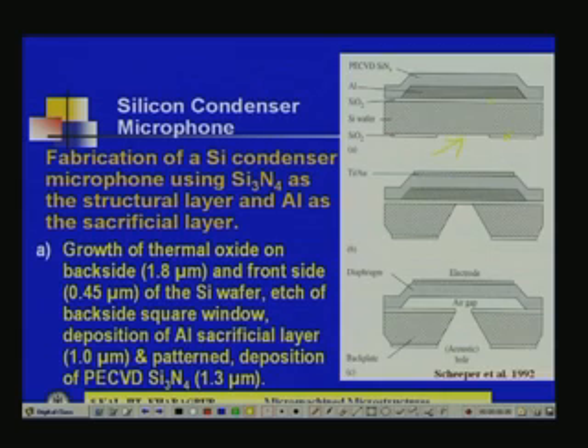Deposition of aluminum sacrificial layer. After that, what have you done? First you did the etching of backside here, then you deposited aluminum. This is the aluminum, this is the aluminum. Then you pattern. 1 micron aluminum is deposited here. Then this aluminum you pattern, then you deposit PECVD silicon nitride, Si3N4, 1.3 micron.